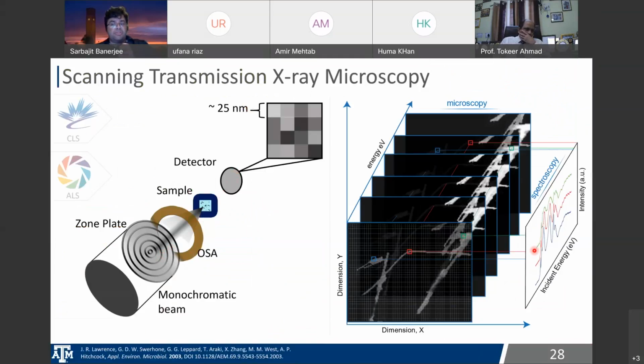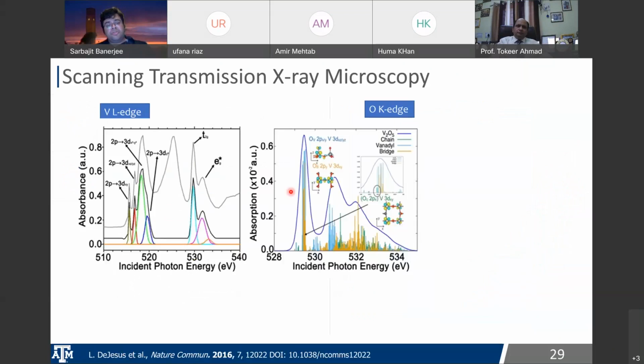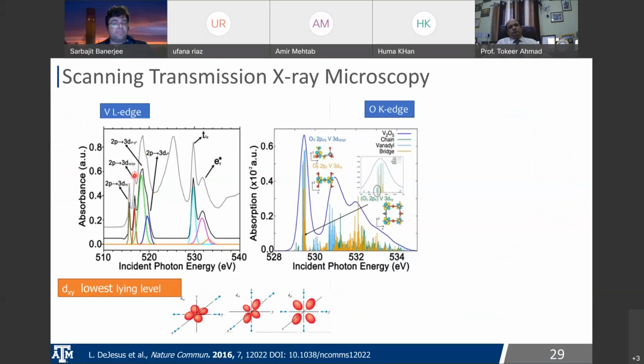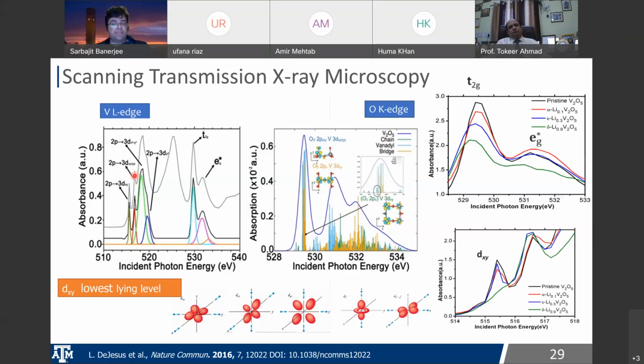And at each point, we get a spectrum, right? An absorption spectrum taken as a function of energy. And so this gives us the ability to image individual particles as lithiation happens. And so this is an example of an X-ray absorption spectrum collected using STXM. And you can see we see very sharp transitions. And we can explain the transitions using basic crystal field theory, right? So you've got the dxy states at the bottom of the band. You've got dxz and dyz states and dz squared and dx minus y squared type states, right? And so as lithium ions come in and reduction starts, what happens is just like you would expect from crystal field theory, the dxy states start getting filled first, then your dxz, dyz states, and then finally dz squared, dx minus y squared states, right?